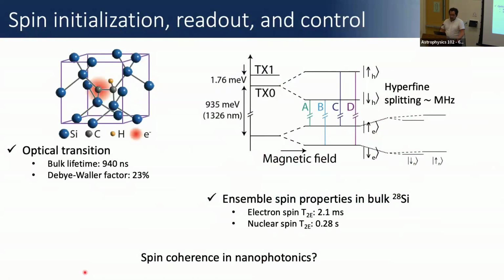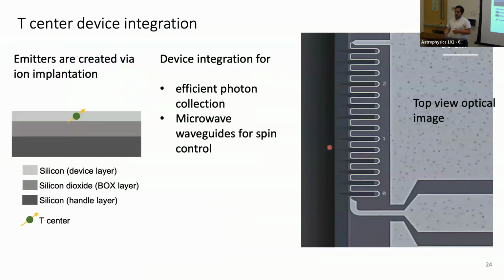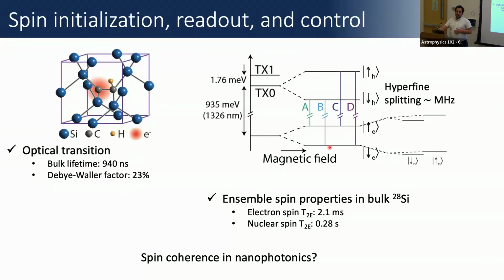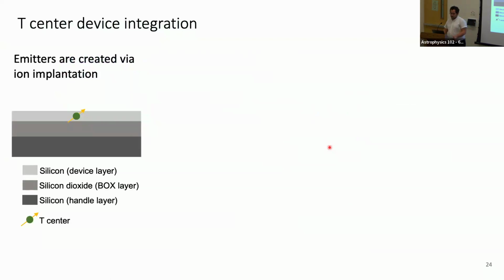All right. Okay, so we have a lot of AMO physicists in the room as well. When you have optical transitions, you can use them to polarize your spin qubits. I told you that the ground state of this defect is an electron spin 1/2. Its g factor is isotropic, really g equals 2, like an electron in vacuum, more or less. But the excited state is this hole spin, which is loosely bound to the defect, and that has some complicated spin orbit interaction that comes from the valence states of silicon and so on. So the excited state has a different g factor. When we apply a magnetic field, we get some differential Zeeman splitting between the ground states and the excited states. That allows us to resolve different spin-dependent transitions, labeled A, B, C, and D. So we can use these to do optical spin initialization and readout.